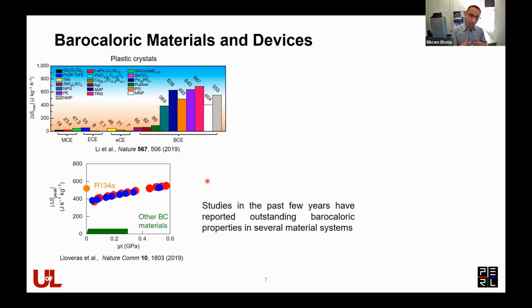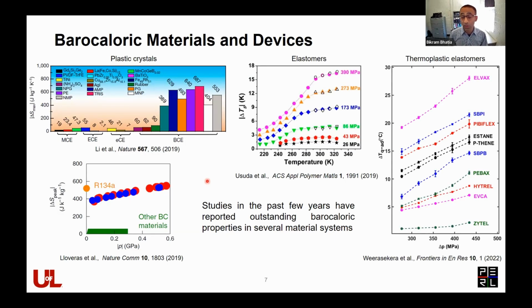There's problems associated with compressibility, also the flowability of the material with high pressures and so on. So there has been a lot of work on these materials with this solid-solid phase transition, but we've mostly been focused on looking at elastomeric materials, which do not have a phase transition, but basically have an entropy change associated with the entangling and disentangling of these long polymer chains in these elastomers. And specifically what we studied were thermoplastic elastomers, which balance the trade-off between high entropy changes and temperature changes with the high thermal conductivity of the material, which is also something that you care about if you're building a device out of it.